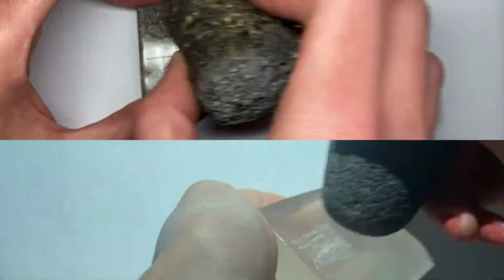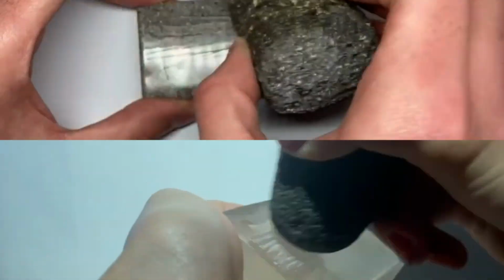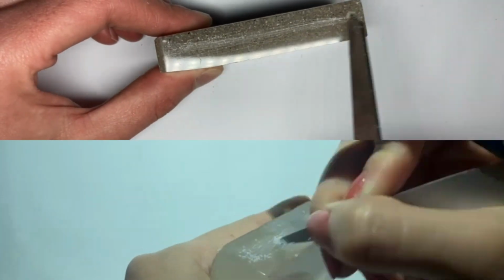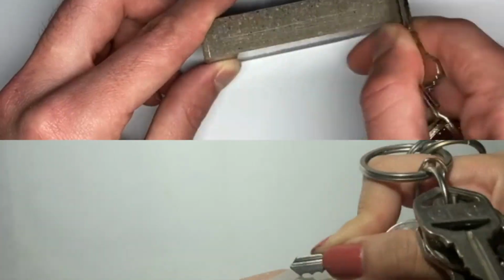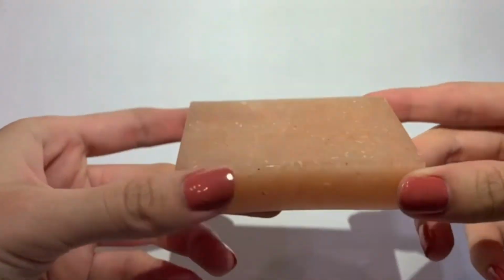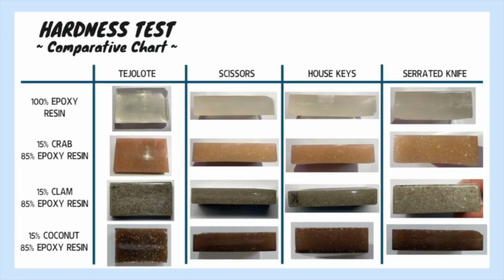Hardness test. The test tube was rubbed back and forward 50 times with a basalt tejolote, steel scissors, stainless steel knife, and an aluminum key on each face of the sample. The surface's damage was the comparison point. After a visual comparison, the crab composite was the material which could better withstand the rubbing. The worst one was the pure resin.